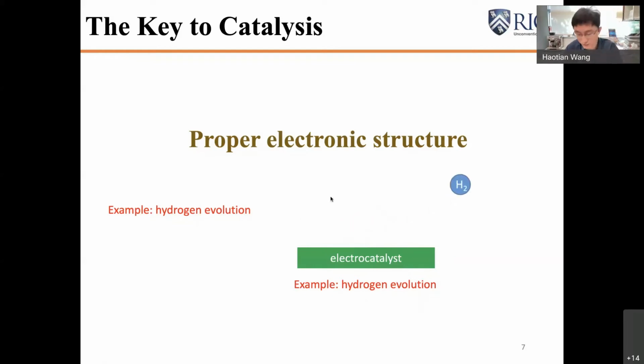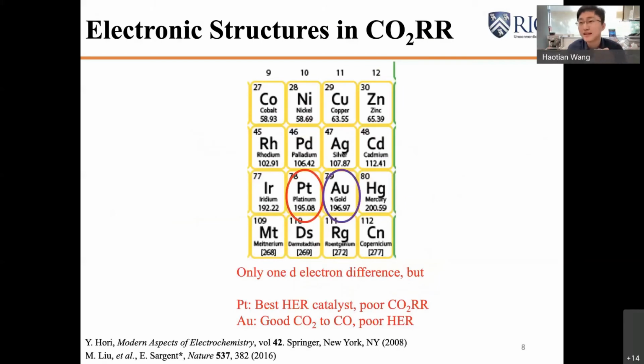This is true in the hydrogen evolution reaction, and it is even truer in CO2 reduction. I usually want to use this simple example to share with you how the electronic property matters in CO2 reduction. As we can see, platinum and gold have only a one d-electron difference. They are neighbors in the periodic table, yet they have very different electronic properties. And as a result, their CO2 reduction performance is completely different. Platinum is still nowadays the best HER catalyst, the hydrogen evolution catalyst, and it never dumps electrons to CO2.